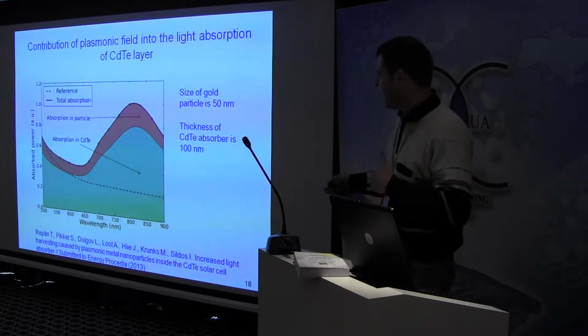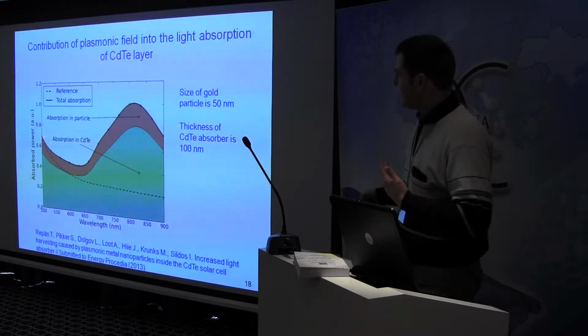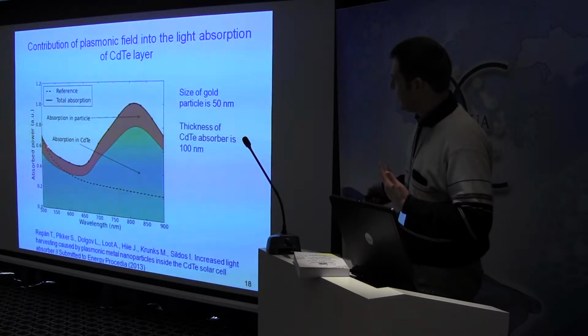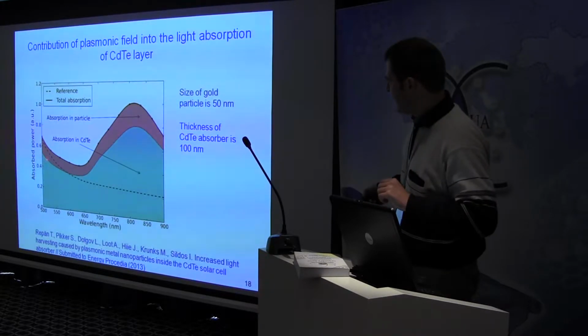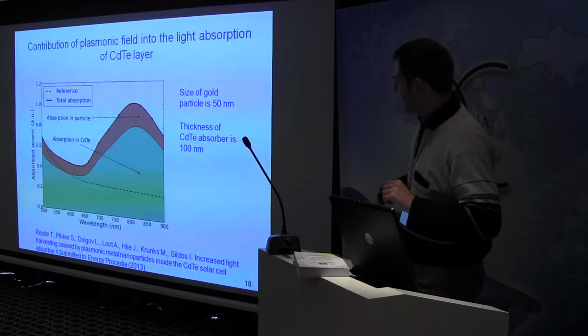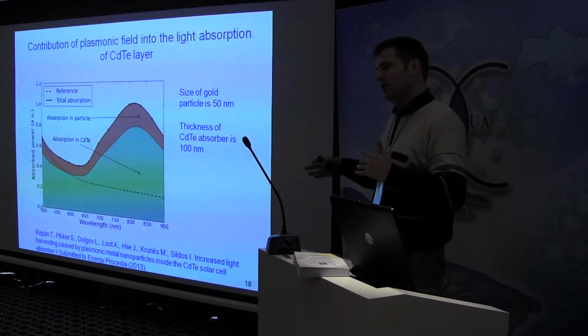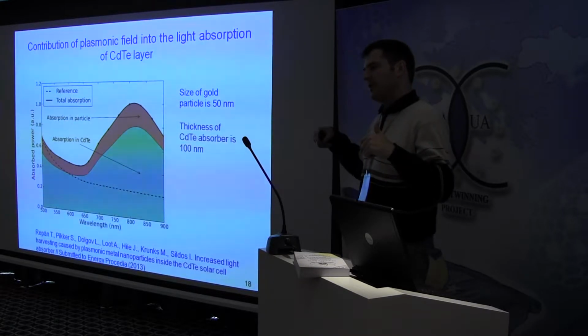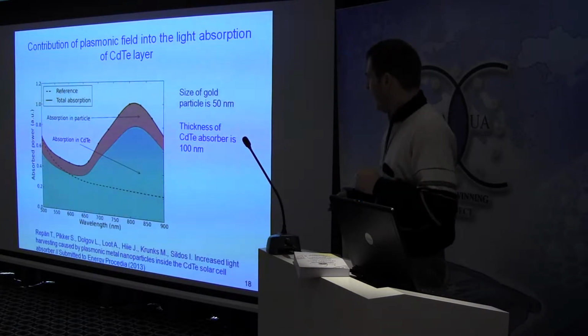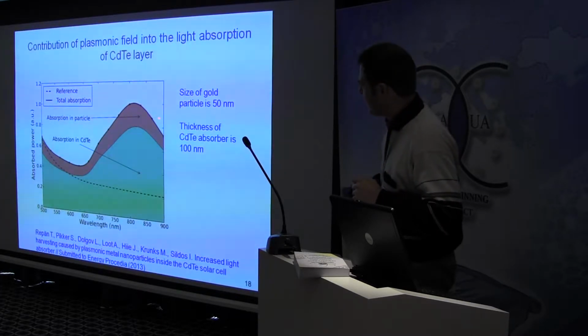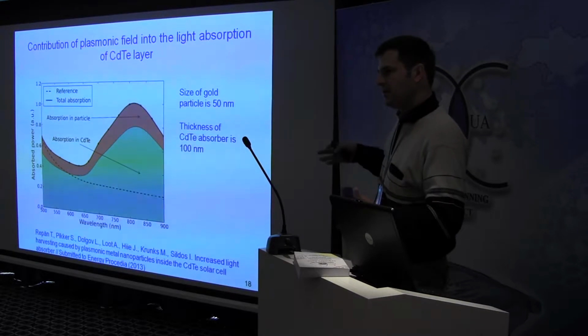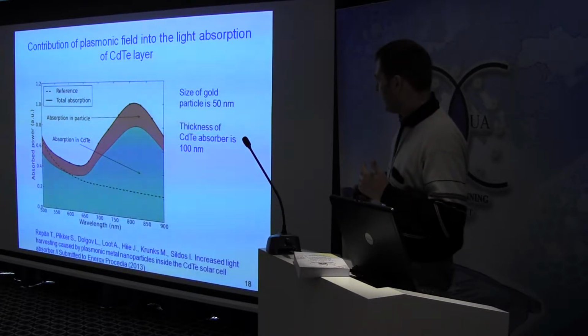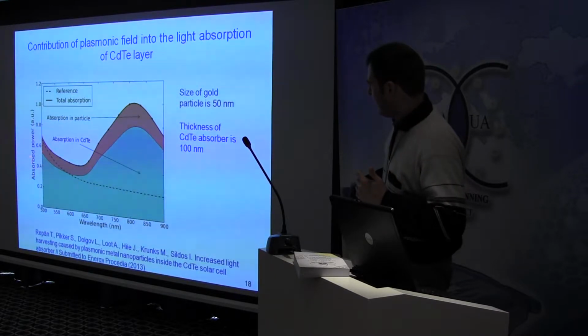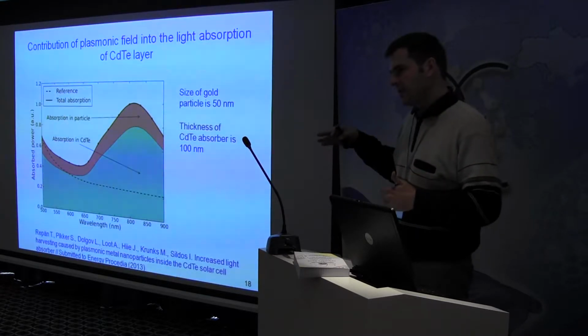And indeed, if we simulate the situation, here you see the dotted line is absorption in the neat absorber layer, and the area under the green is absorption in the host medium, which has the locally enhanced plasmonic electric field inside. And this brownish area is the absorption in the metal itself. It means that it's not useful for us, but it's marked here also. If you compare the area under the dotted curve with the green area, we obtain almost 2 times enhancement in absorption.